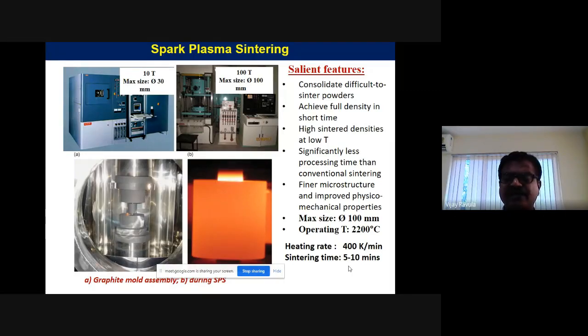But then how do we consolidate? We have to do it at higher temperatures, but in very little time, very quickly. So we need a process where the temperature rise is very fast, something like a heating rate of even 400 Kelvin per minute. That is called spark plasma sintering. You can see that we have both types, 10 tons and 100 tons. The 10 ton is for conventional research, and with the 100 ton we can make some components.